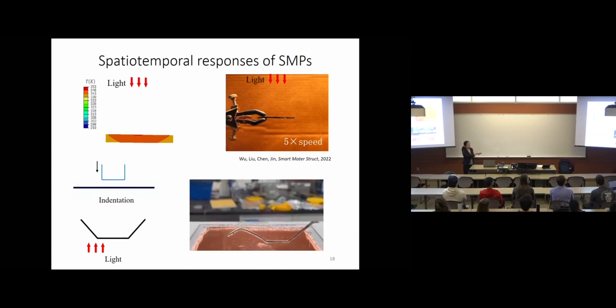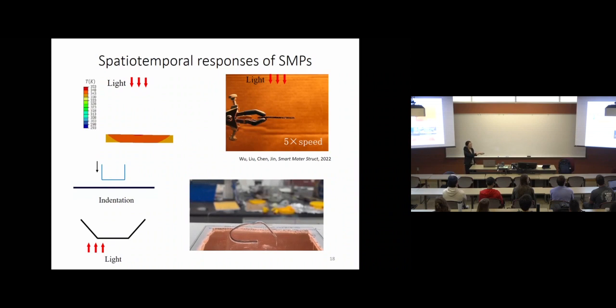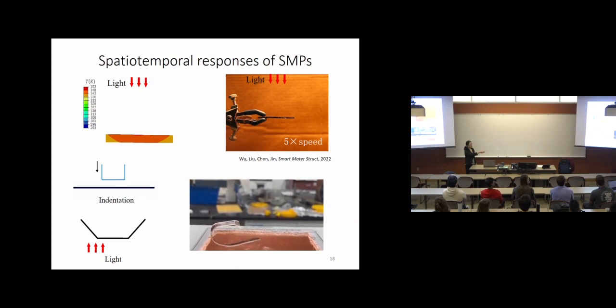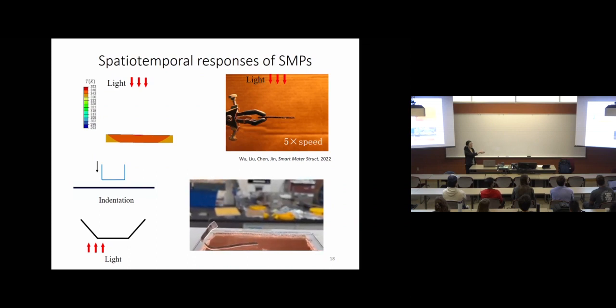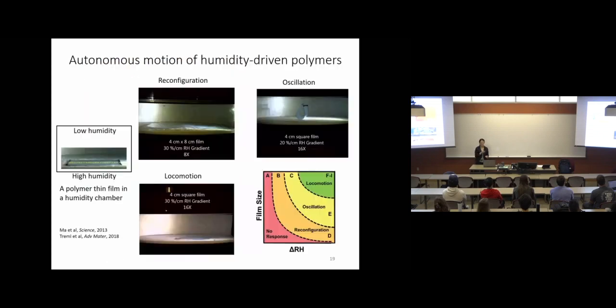Because we shine light more towards the left, the left side bends early. Then it can trigger the flipping over of the material, and on the other hand, now this right side starts to bend. And eventually, because everywhere the temperature goes above Tg, it can eventually completely relax. So as you see here, the whole process is governed by kinetics. And we are not changing the environment at all, but it can undergo this complex motion.